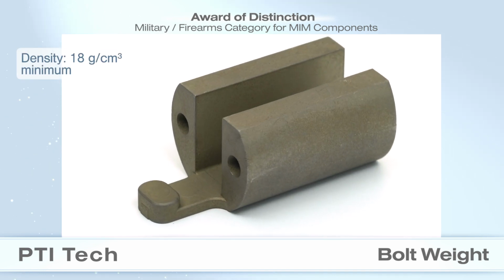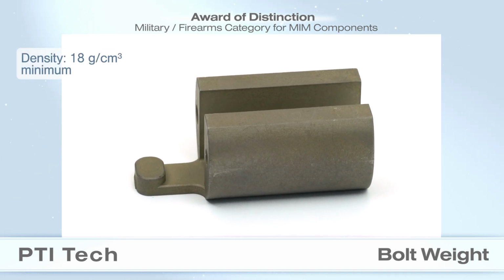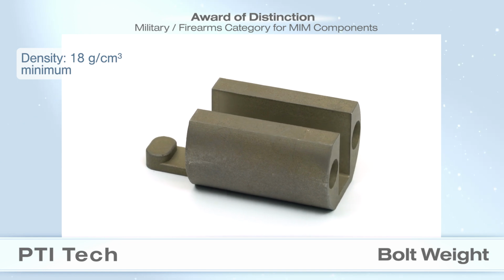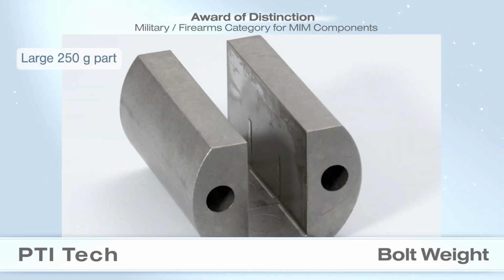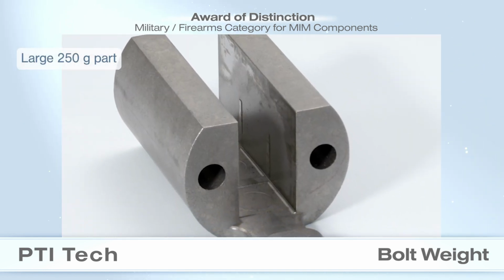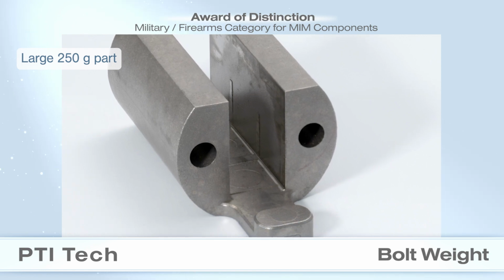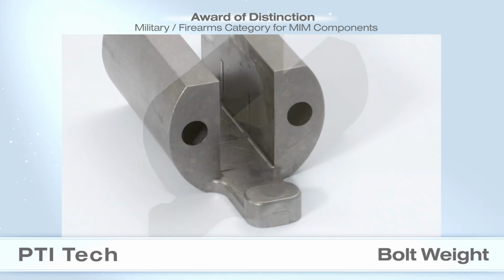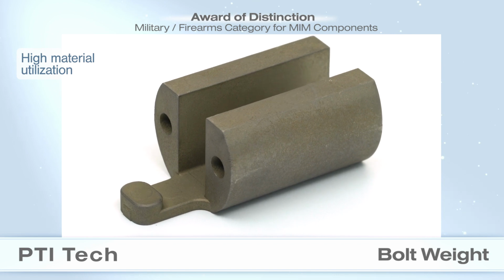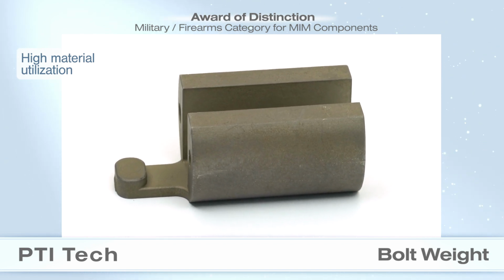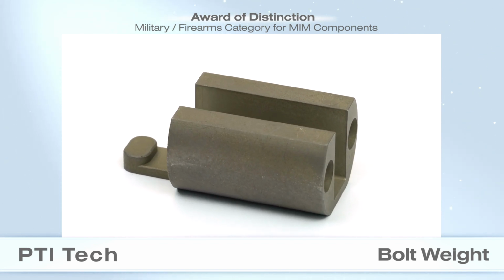A 95% weight tungsten alloy was selected to result in a relative density of more than 18 grams per cubic centimeter. Sacrificial support ribs were added to mitigate sintering distortion and were CNC machined from the final part. Machining the part from bar stock would have resulted in over 70% scrap, considering an 1,100 gram bar stock would be machined to a 250 gram finished part.